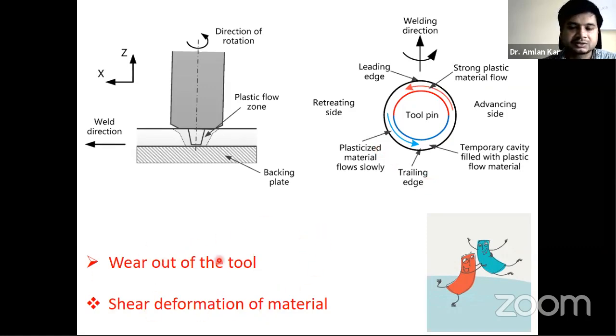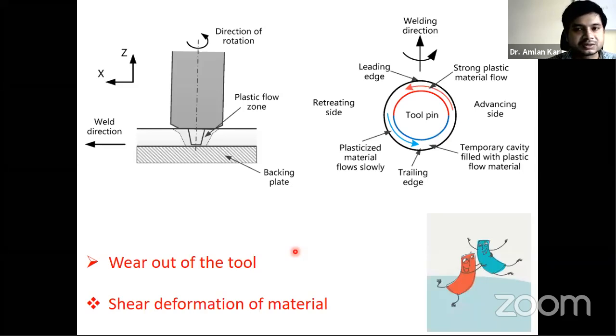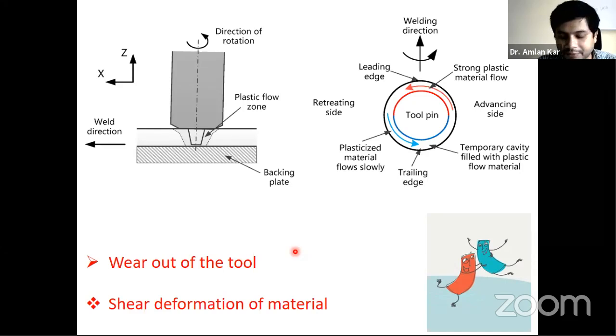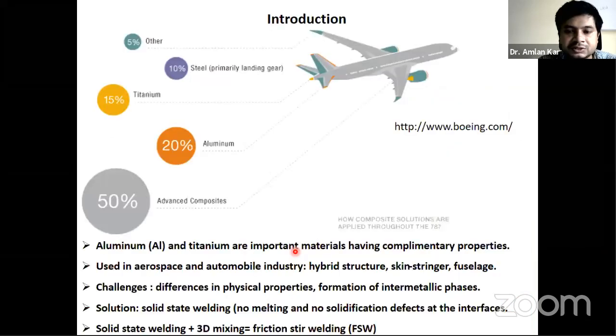And because of that, two phenomena could be possible. One is wear out of the tool. If the load bearing capacity, or the shear strength, of the tool is lower than the shear strength of the deforming material or the applied shear stress, then there is a wear out of the tool, and in the other case there is a shear deformation of the material, okay, at low temperature.